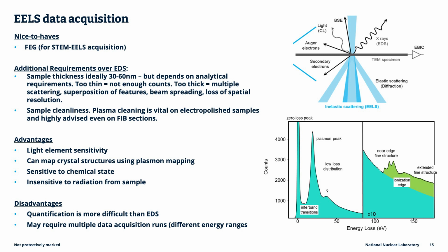As the electron beam passes through a sample, it loses energy. EELS analyzes the energy which has been transmitted through the sample. We have an intense peak in the spectrum where no energy has been lost. In the low loss region, we get plasmons, which are related to the energy loss of the electron as it goes through the sample. Measuring the intensity in the plasmons allows us to measure thickness, as we've already heard. And the shape of those plasmons can inform us on which phases are present, or at least their distribution.